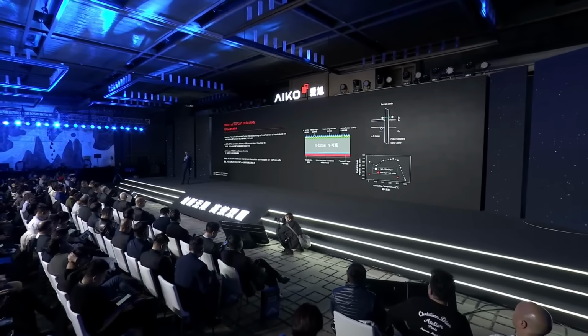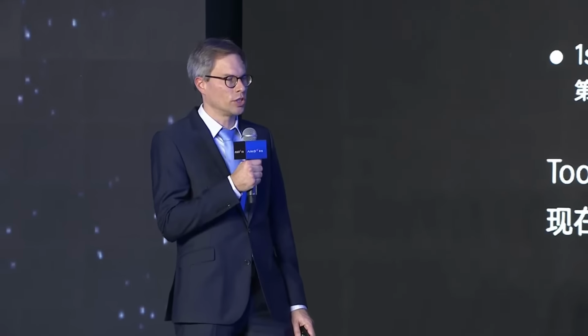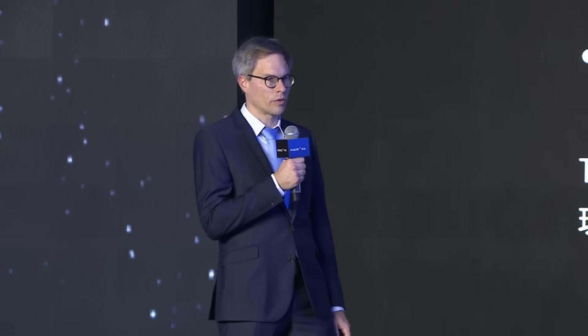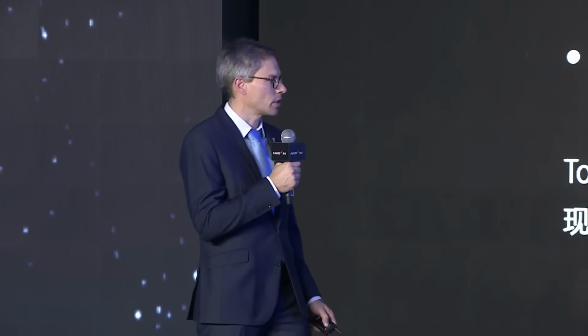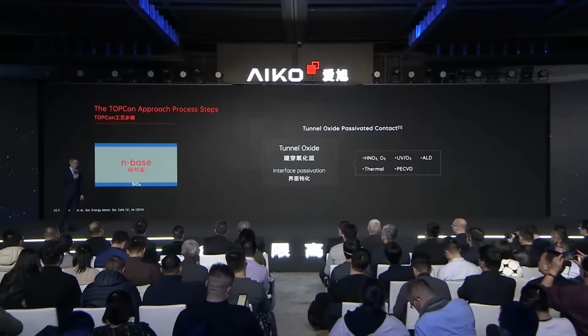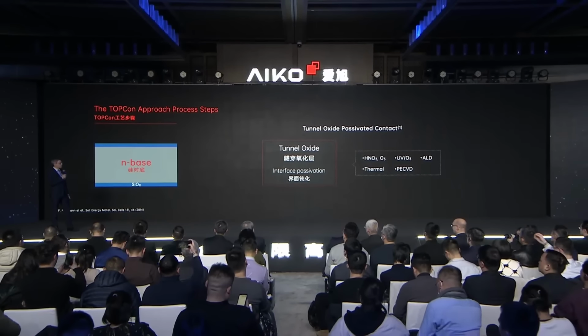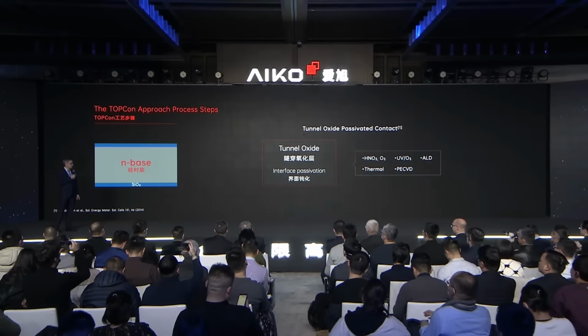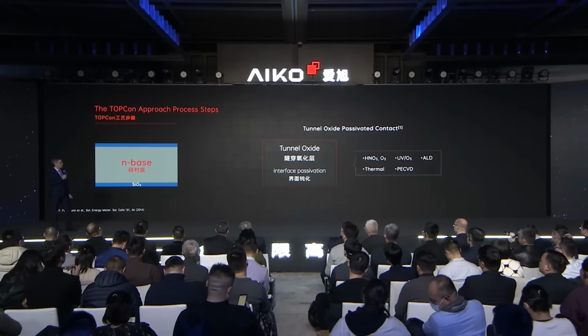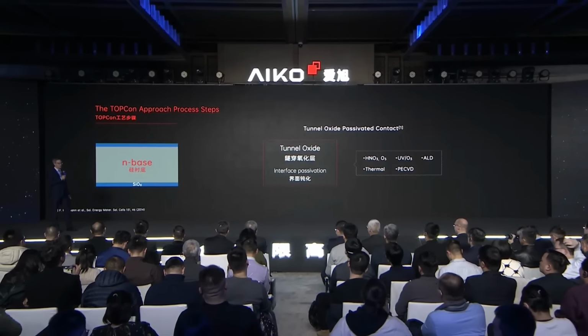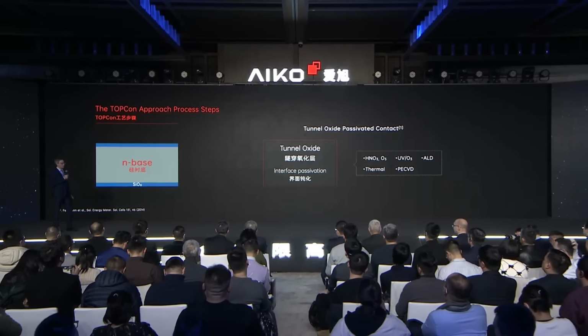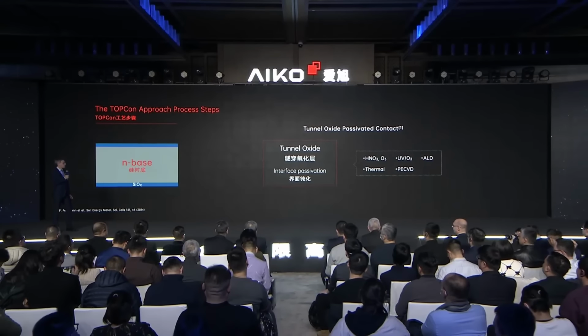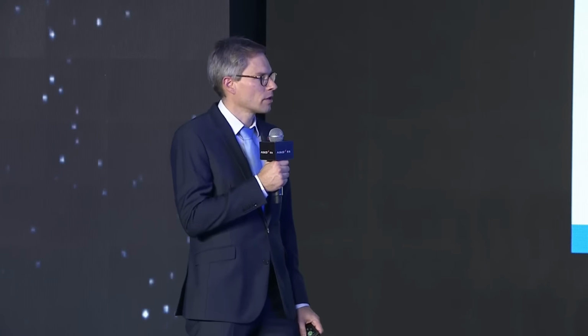Today in the industry we see two mainstream technologies for TOPCon, on the one hand LPCVD and on the other hand PECVD. Let me guide you quickly through the main process steps for making a polysilicon contact. Here you see a sketch of a symmetric lifetime sample. The first process is to grow a very thin tunnel oxide layer, on the order of 1 to 2 nanometers. We can use different means. Most popular is thermal oxidation for the tunnel oxide.